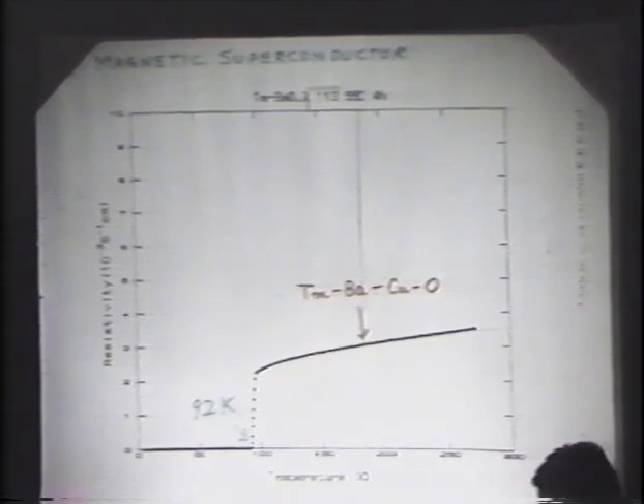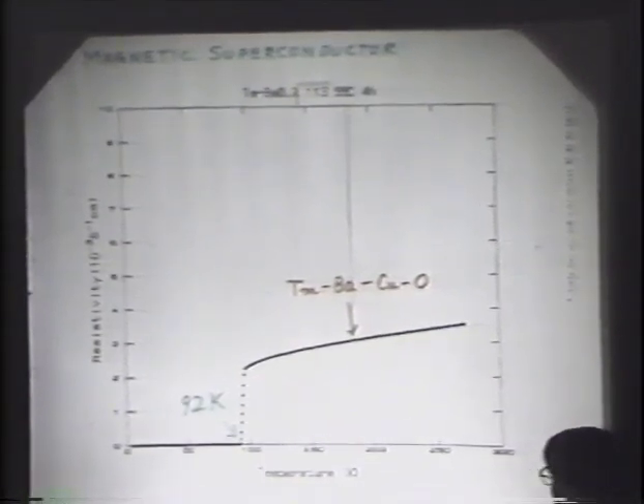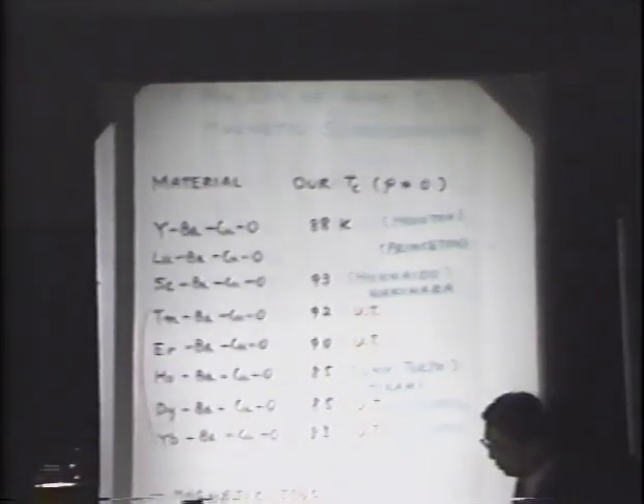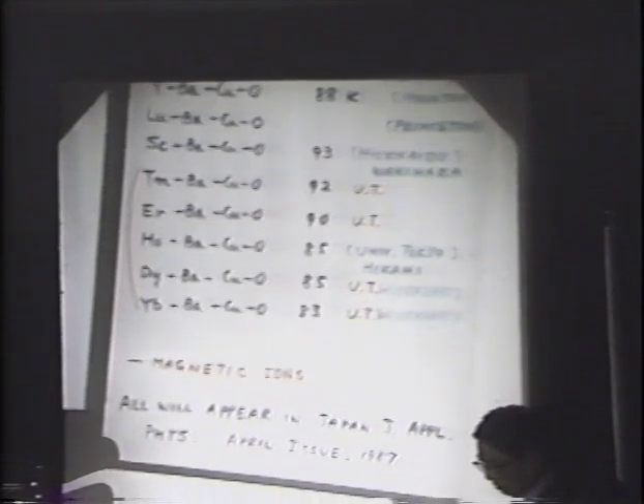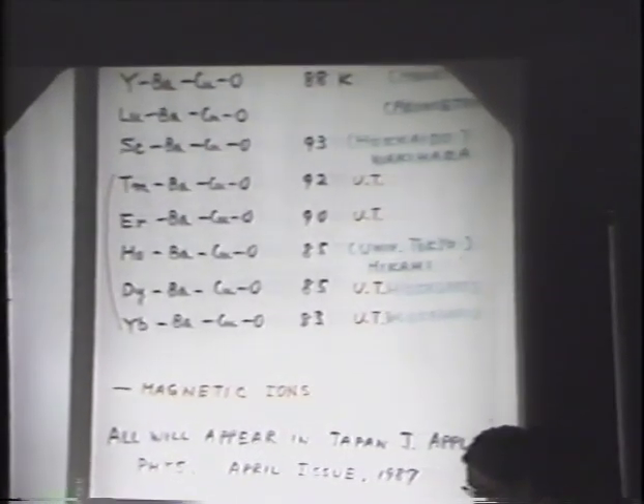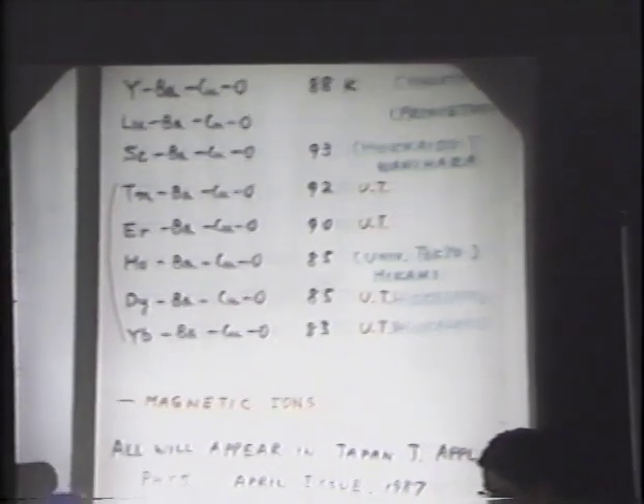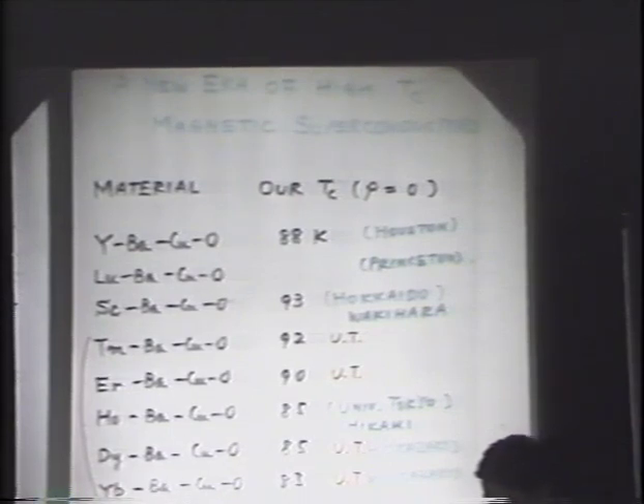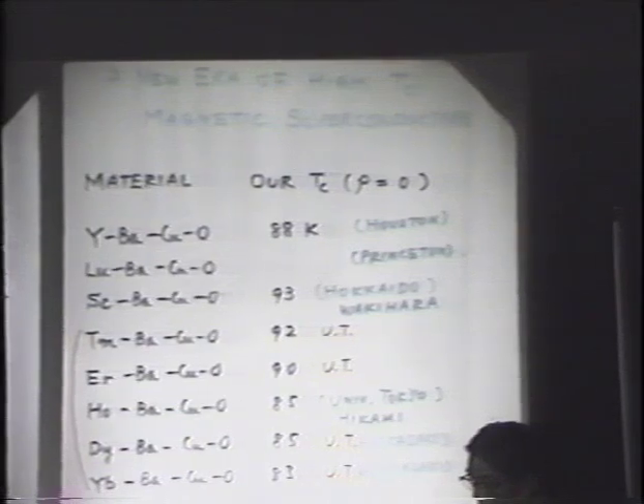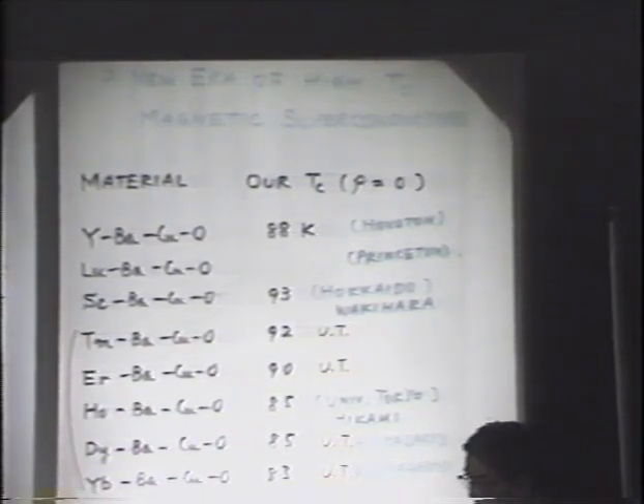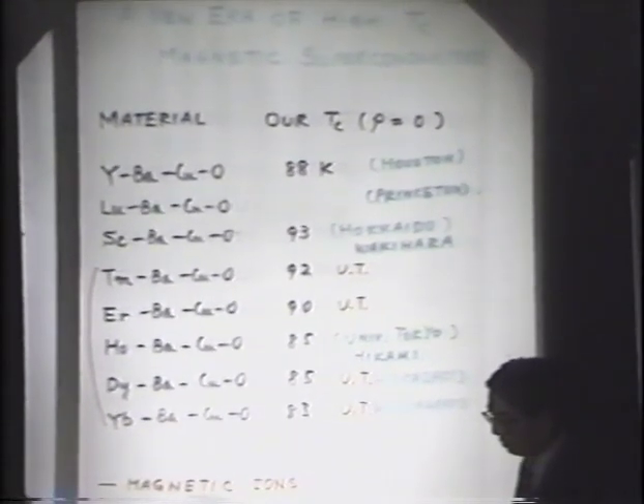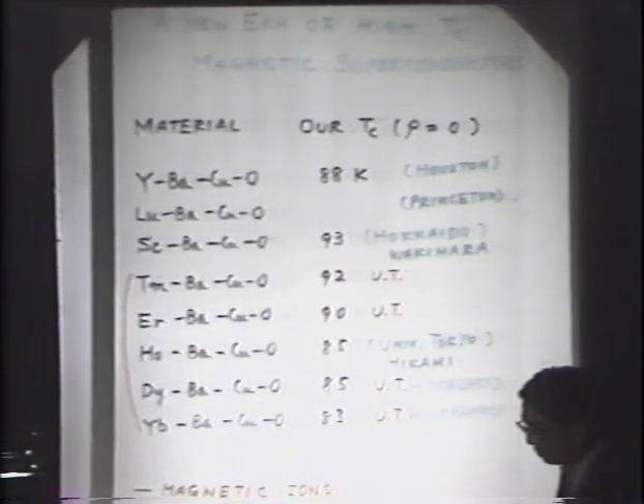It is very interesting. They have magnetism at temperatures beyond the critical temperature. So we can say that they are a new type of high TC superconductors, and at the same time, a new type of magnetic superconductors. It is surprising that the magnetic moments of these lanthanoid elements do not affect the superconductivity at all. This fact may be related to the layer structure of these crystals. And this may provide a basis to clear up the electronic structure of these high TC superconducting materials, as well as the mechanism of superconductivity. Thank you.